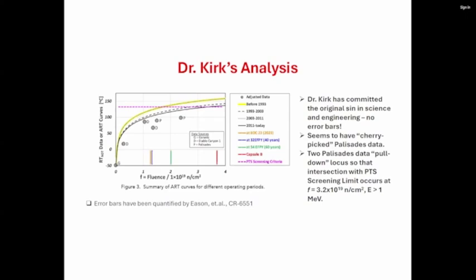Here's Dr. Kirk's analysis. The points marked D are for Diablo Canyon. There's a generic point at minus 50 degrees centigrade. And then the first point up from that is capsule S, then capsule Y, capsule V, and then two data points that were taken from Palisades. You can see that those data points from Palisades tend to bend down the curve, so that the curve begins to flatten out and run parallel to the screening criterion.